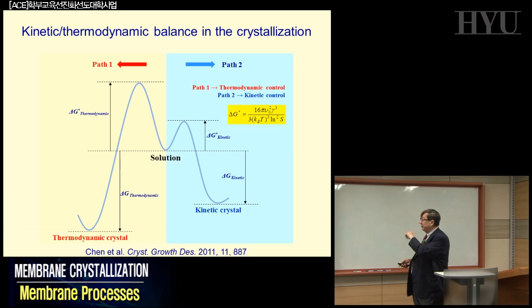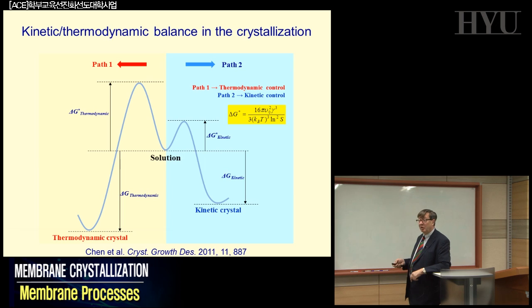That's quite interesting because this is true, and we are working, we means you, these good students, are working to try to confirm this in very different kinds of situations. That is quite interesting, the most interesting aspect of membrane crystallization, because in this case the possibility to control the metastable heterogeneous phase is related to the properties of your membrane, to the porosity, to the roughness of the membrane surface, to the size of the pore, etc., at a different level of sophistication, because it depends on the depth of the pore, for example, in some cases, etc., etc.